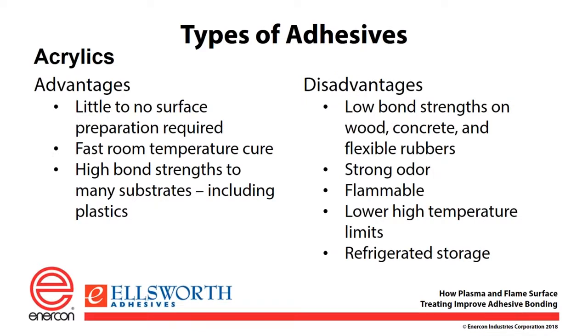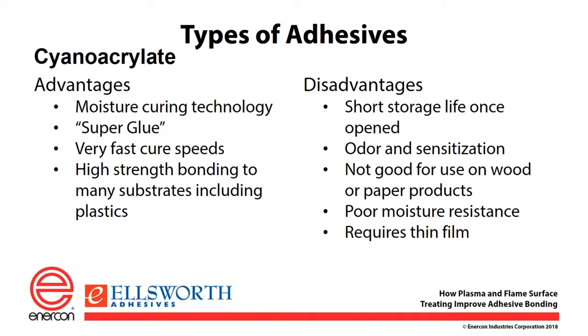Acrylics have a major advantage in that they require little to no surface preparation. They're also very fast curing, and they offer excellent bond strengths to many substrates, including plastics. Some disadvantages would include they're not very good for bonding wood, concrete, or flexible rubbers. They generally have a strong odor. They're flammable. They have lower high temperature limits than an epoxy, although they would be higher than a polyurethane. And they typically require refrigerated storage.